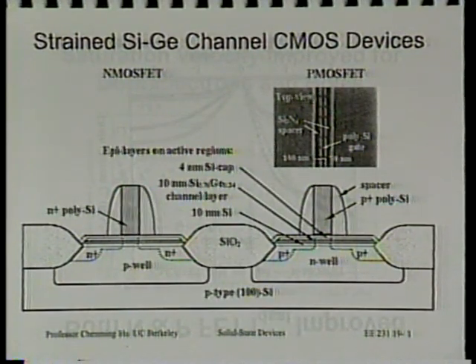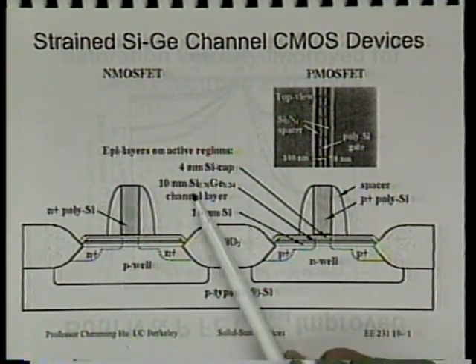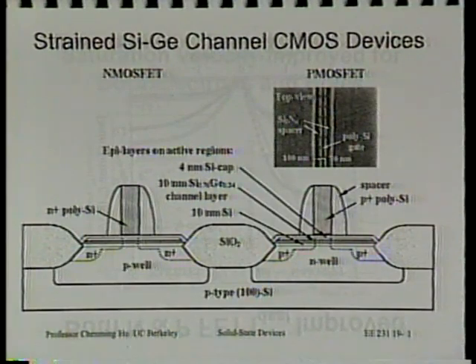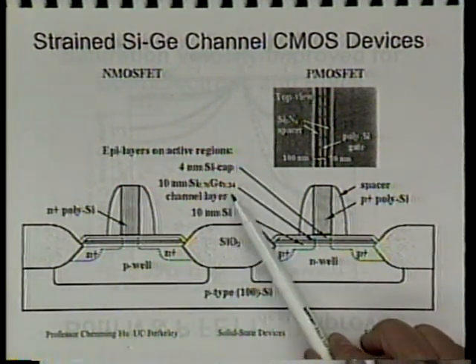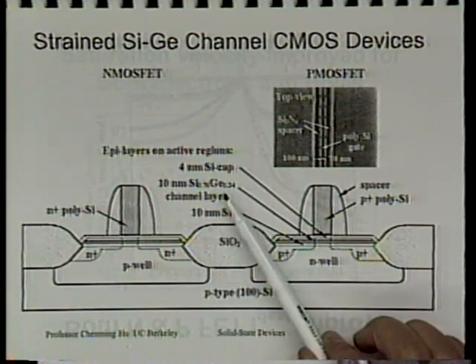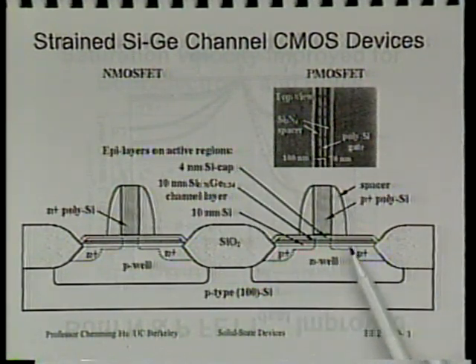It's 10 nanometer. Here we use 76% silicon, 24% germanium. If you use a higher percentage of germanium, the benefit will be greater, but it will also be harder to grow the epi film. And this happens to be just about the concentration used in the silicon germanium bipolar transistor, by the way. All right, and all these things could change as we learn how to do this, of course. And so this is the silicon germanium film.